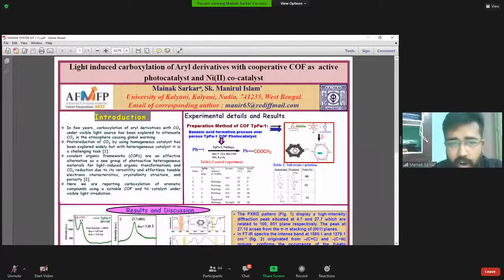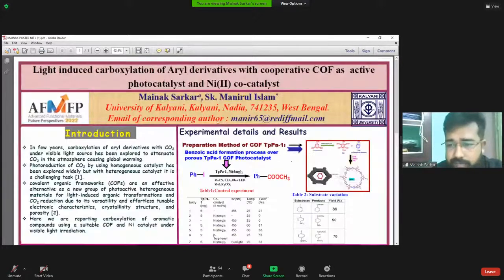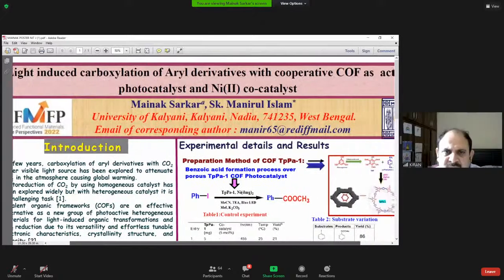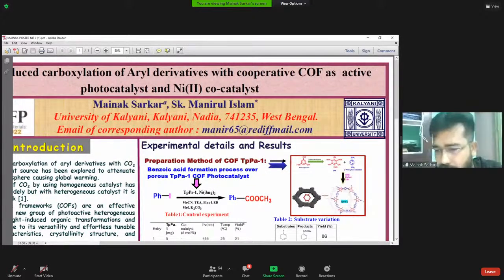Okay, basically, this is the COF. Is this visible, sir? Yes, ma'am. Okay. Basically, this is the structure of the COF, a covalent organic framework. It also has pi conjugation, and it is very effective for light-induced reactions. We have prepared this by condensing Tp, triformylphloroglucinol, and paraphenylene diamine, reacting them using PTSA, paratoluene sulfonic acid, with water as a solvent, hydrothermally in a Teflon-lined sealed autoclave at 90 degrees for 16 hours.